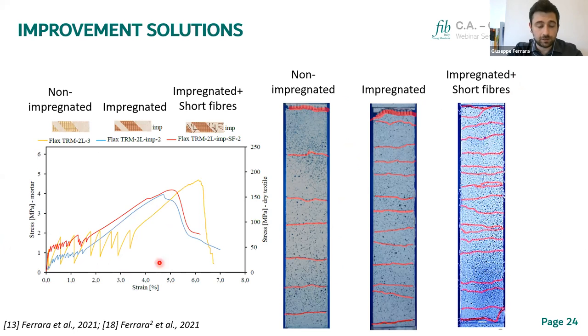Of course, we can see that the crack pattern on the impregnated specimens is much denser than the one exhibited by the non-impregnated specimen. And if you look, for example, at the strains, which are a very significant aspect in view of application to structural elements, the impregnated flax confers a better mechanical response to the system by significantly reducing its deformability.